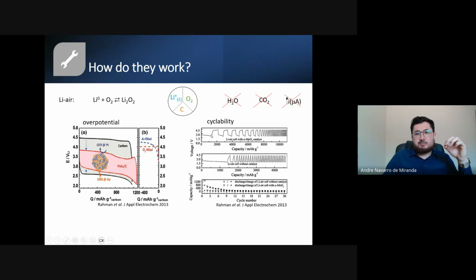Another problem for this system is cyclability. Here we have a cell where we can see the cyclability with the catalyst, and here without the catalyst. We can see that the cycles start to lose capacity over time. When we see the number of cycles of this type of battery, we see about 30 to 50 cycles. If you compare with lithium-ion batteries that have 3,000 cycles, 5,000 cycles, this system still has limited capacity in terms of cyclability and number of cycles. Today, we have 100 cycles, 200 cycles, but we are still far away from 3,000 cycles.